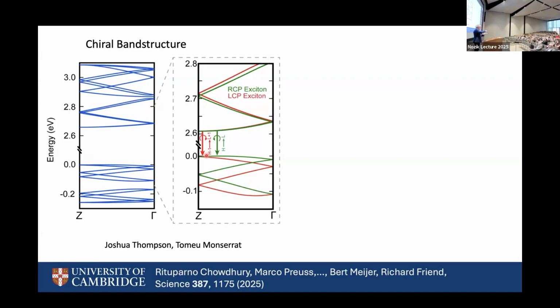circularly polarized electron or hole states. They can be right-handed or left-handed. At high symmetry points in the Brillouin zone, they're standing waves, but as we move away from the high symmetry point, they disperse differently. We have one electron state that has the same handedness as the actual structure, which disperses more quickly, but the other has the handedness that goes against the handedness of the structure.